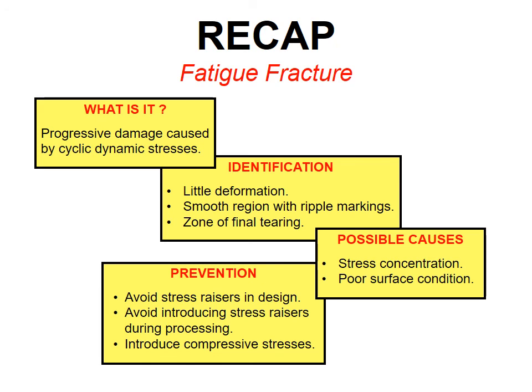Now, before going into our last failure, creep, let's summarize and recap on what we have learned on fatigue. It's the failure of a metal under a cyclical dynamic stress. It shows little or no deformation, and its fracture surface normally shows two areas, where one portion is smooth displaying beach mark striations spreading out, and the other portion the final tearing zone. The cause is due to stress concentration originating from stress raisers like notches, keyways, screw thread, machining, and other irregularities stemming from poor surface conditions. And to prevent fatigue as far as possible, avoid stress raisers in the design stage and avoid introducing stress raisers during processing. Alternatively, we can instead try to improve the surface condition by introducing compressive stresses through methods like